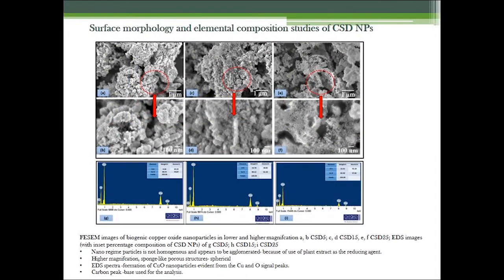Coming to the SEM analysis. The surface morphology and elemental composition of the biogenic copper oxide nanoparticles were analyzed using SEM and EDS micrographs. The distribution of the nanoparticles is not homogeneous. It appears to be agglomerated. In all the images, you may observe the nanoparticles are found to be agglomerated because of the use of plant extract as a reducing agent. Then the surface morphology of the synthesized nanoparticles is found to be spherical in shape at higher magnifications.